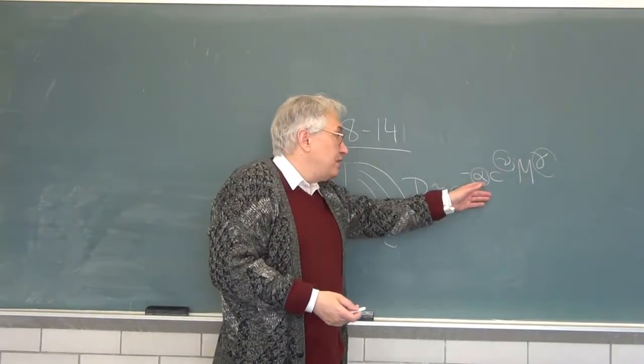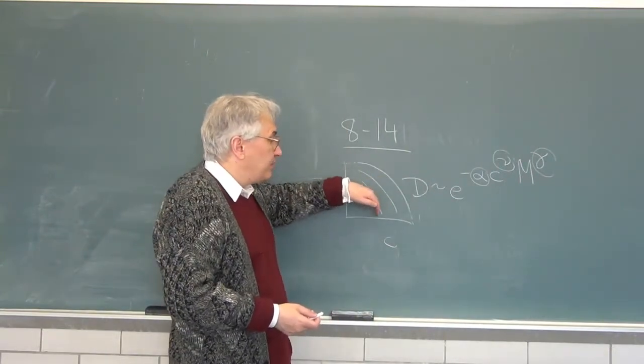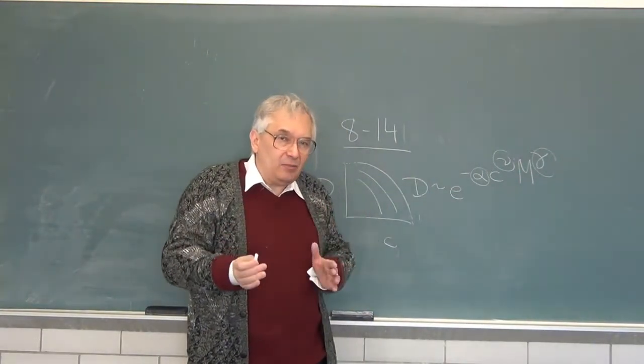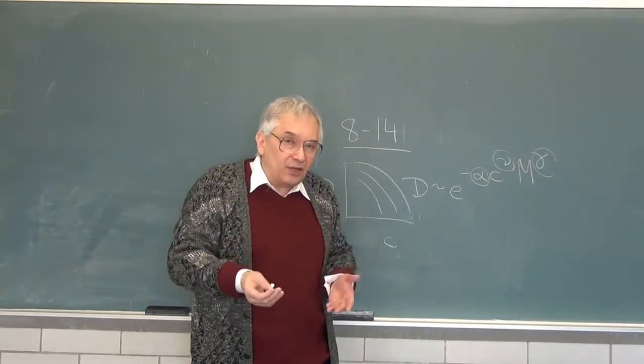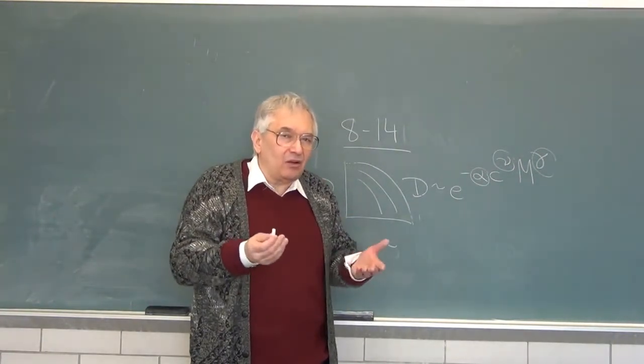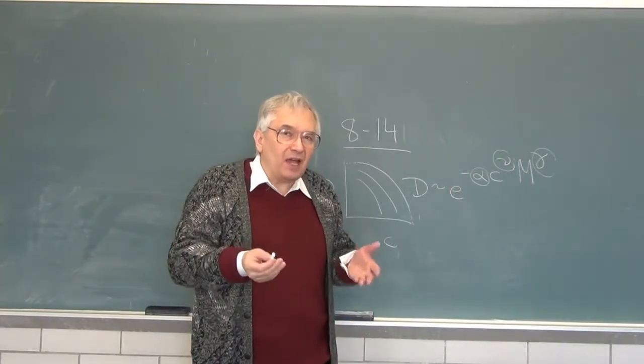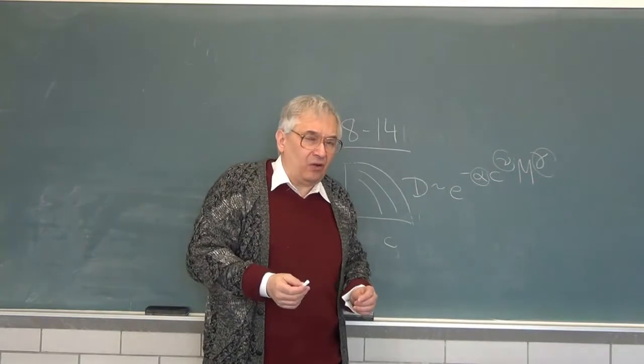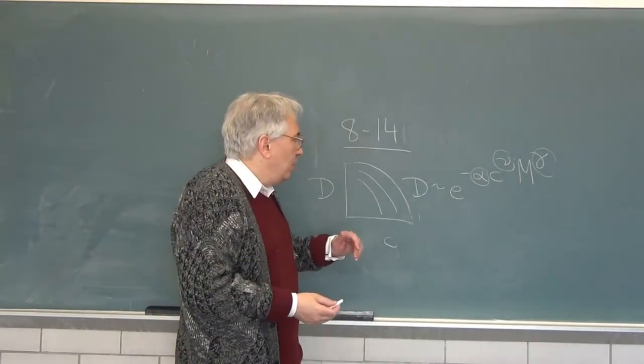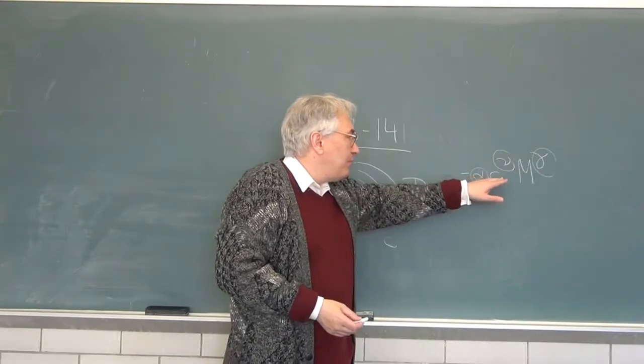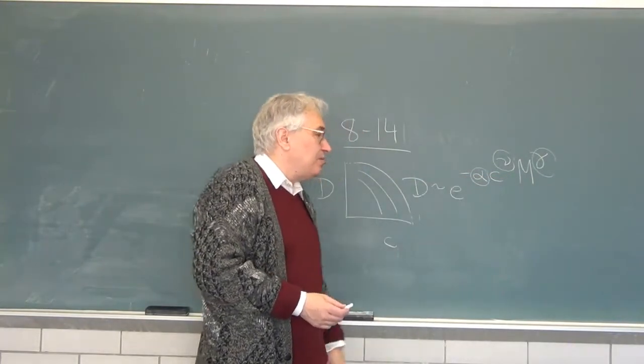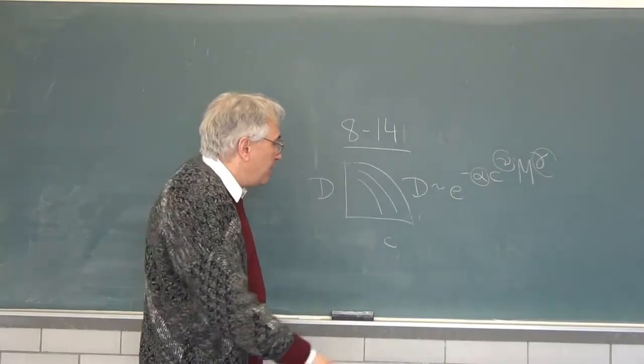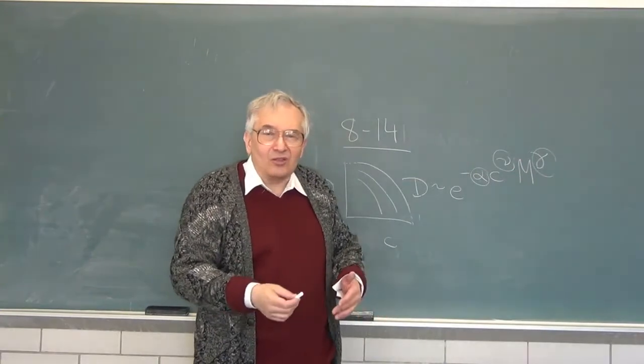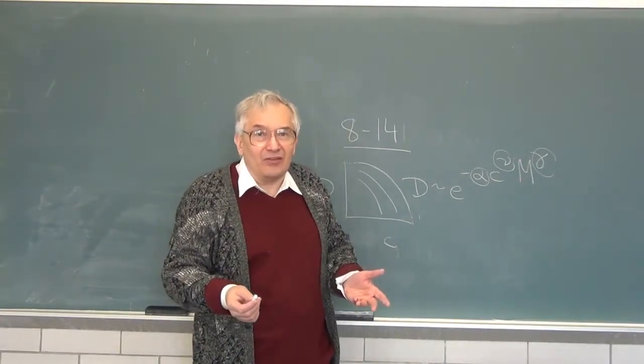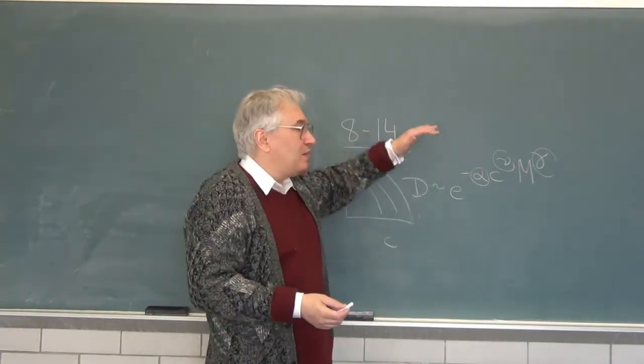Furthermore, this form, as is seen from these curves, is successful at simultaneously reducing both the concentration and the molecular weight dependence to what is in fact one single curve. You might say, curve? It looks like a bunch of curves. Well, D here is really a function of two variables, concentration and molecular weight. And therefore, you could imagine doing a three-dimensional graph, or in some science fictional future in 15 years, having the holo blackboard display,